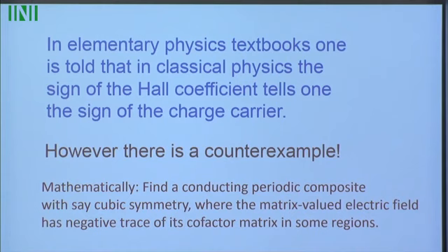So there's actually a counterexample, and from a math perspective, it amounts to finding a conducting periodic composite with, say, cubic symmetry, where the matrix-valued electric field, this is an idea of Luc Tartar, is that you should look at the electric field corresponding to 3 directions of the applied field, and that gives you a 3 by 3 matrix-valued field. And if you can find that it has a negative trace of its cofactor matrix in some regions, then you're done by perturbation theory.